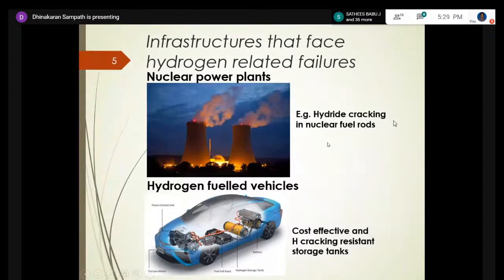One example is hydride cracking, which is also because of hydrogen getting into the metal. In nuclear fuel rods, they use zirconium alloy. That is a hexagonal close packed crystal, and that alloy forms hydrides with hydrogen. That is a brittle phase, and it starts to crack, which is very, very dangerous. We don't want that, so people work on zirconium alloy to prevent any failure.